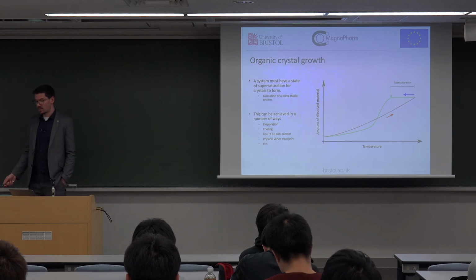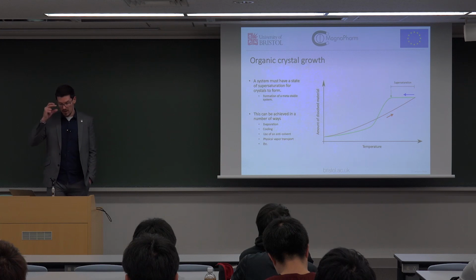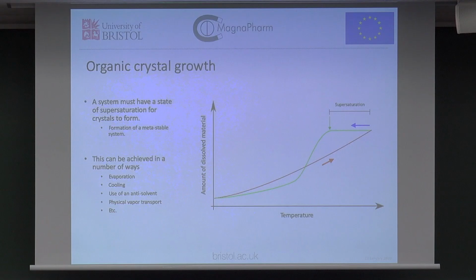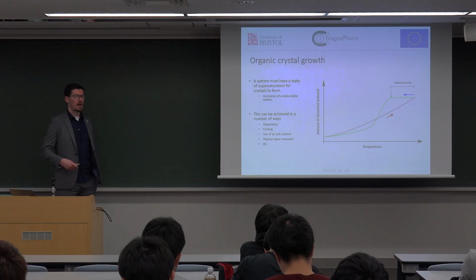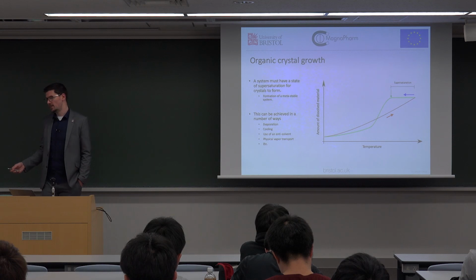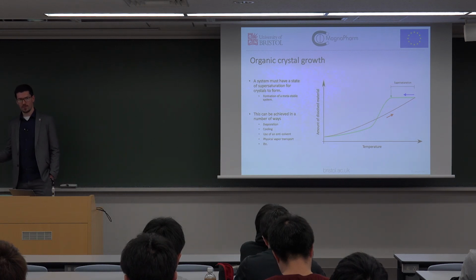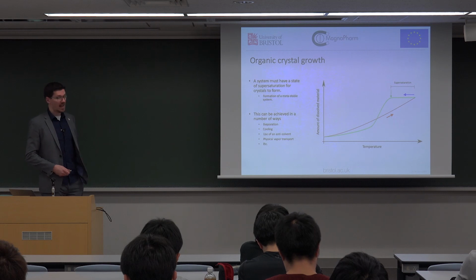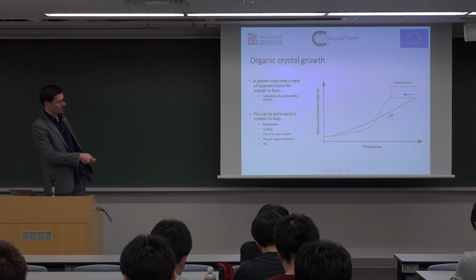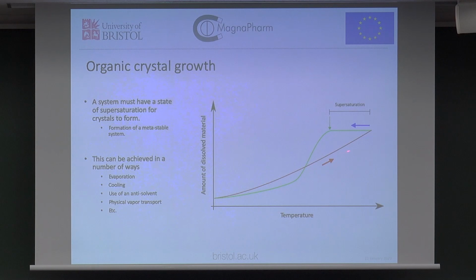So organic crystal growth is basically a function of making a supersaturated system, be that in solution, or in physical vapor transport. Typically, a crystallization experiment is you dissolve your solute in a solvent, you then increase the supersaturation. It can be done in a number of ways. You can have an evaporatively driven crystallization where you let the solvent come off bit by bit, and that increases the supersaturation here. So you dissolve more and more and more as temperature increases, and then you filter out any